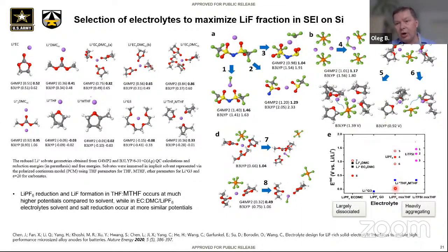So in this case, what we settled on was lithium with THF, methyl THF, which has a low reduction potential, as I'm showing here. So that's lithium THF and methyl THF. They're close to 0. If we go to a more realistic scenario of a complete solvation shell, it's about 0.3 volts, right? So THF would decompose, but only after the majority of silicon was lithiated. And before that, this electrolyte is heavily aggregated, so clusters like this are present, and reduction of the salt would really dominate.